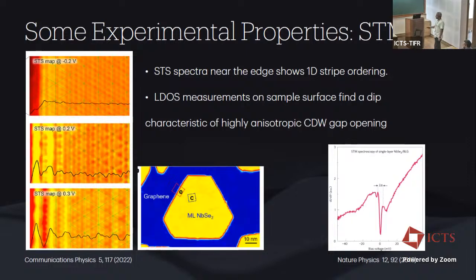Now, in this particular paper, they argued that these stripe-like patterns are not a simple result of some kind of Friedel oscillation happening from these edges, and this they argued based on the fact that the stripe-like patterns also maintain a 3-unit cell periodicity. So they tried to show from some simple calculations that from a Friedel oscillation, since the physics would be governed by the inverse Fermi wavelength, this type of pattern would not be expected.